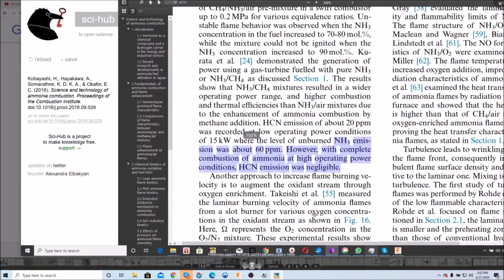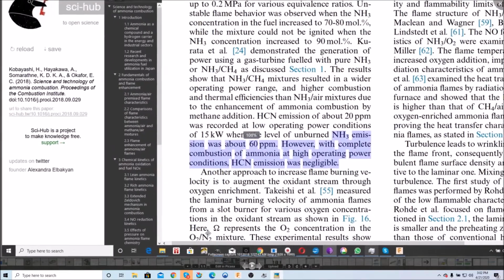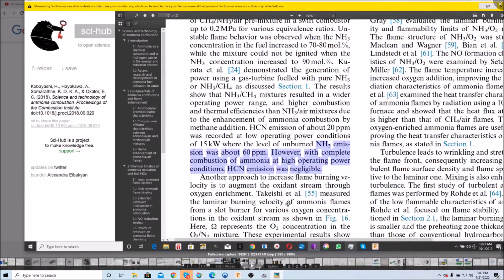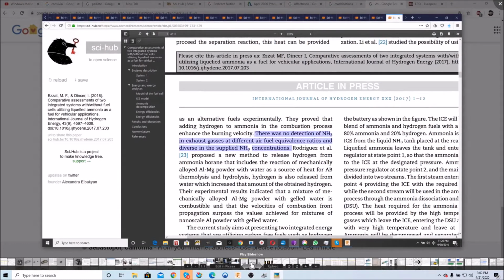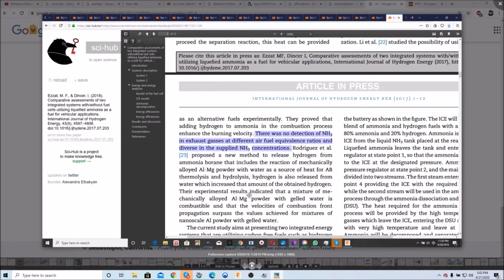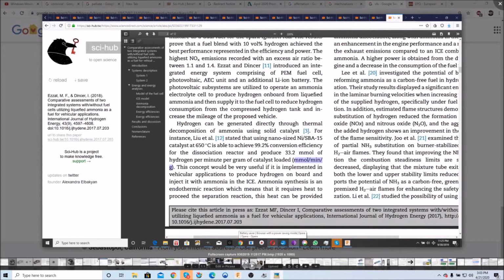Using a reactor, we could crack, let's say, 80%, and that 20% ammonia is going to be nearly completely combusted because we have so much heat, so much energy from that hydrogen that's going to overwhelm that ammonia fraction, and the residual concentration is likely to be much, much smaller than if we burn pure ammonia. In some cases, they didn't find any NH3 concentration in the exhaust gases. If you get the air-fuel ratio right, you get the equivalence ratio right, if you have high combustion temperatures, I imagine you could probably reduce it to very minimal levels.